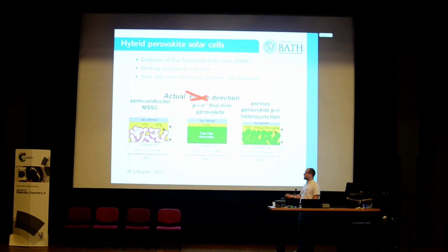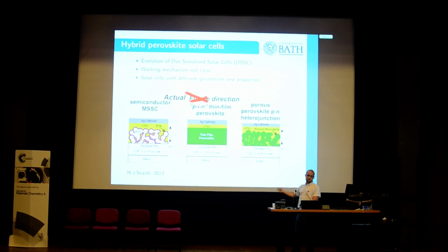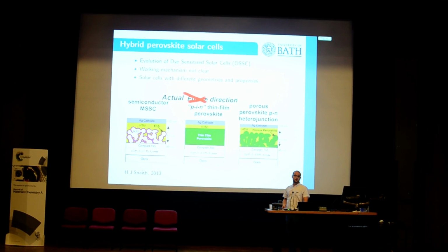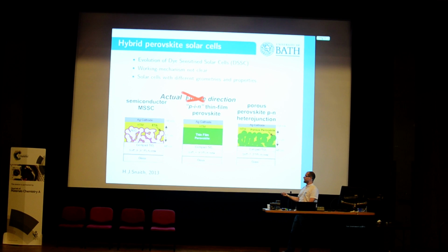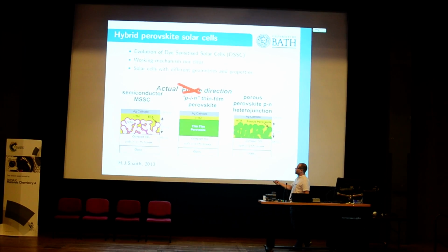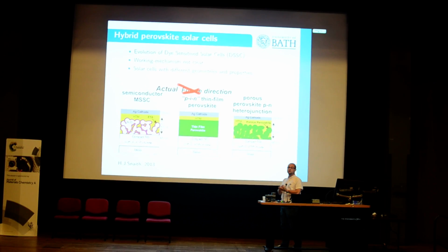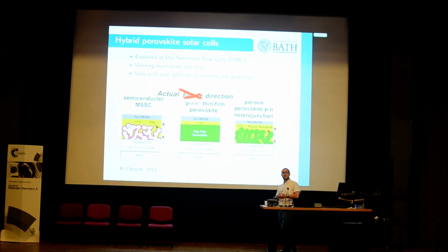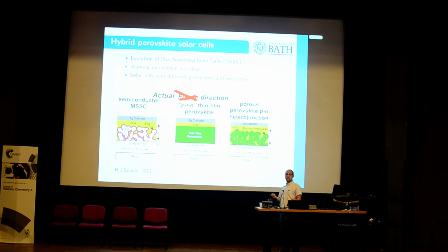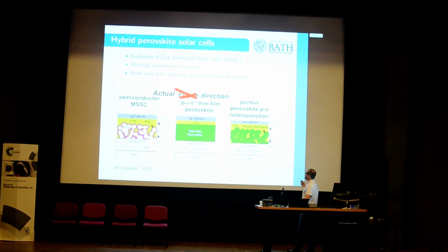The one I showed yesterday, and was talking about the future direction of the field. With this, the future of 2 years ago is actually nowadays research, and it's possible to build solar cells with a completely different principle behind. So we can deposit the perovskite on a semiconductor, with a porous semiconductor that acts as a scaffold. We can create a PIN junction, a thin solar cell, but we can also have a bulk, well, a heterojunction PN solar cell.